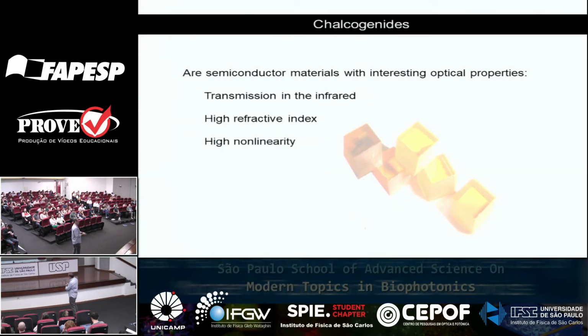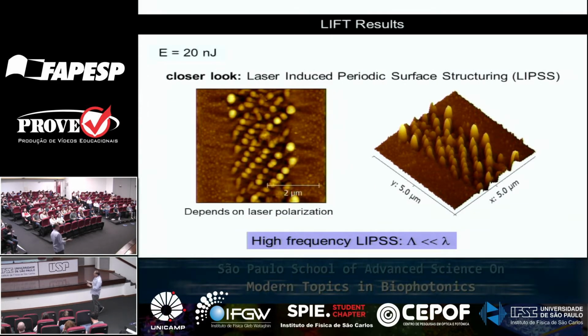In this case, I'm just going to show results for chalcogenides. Chalcogenides are interesting materials, mostly for telecom applications in the infrared. They are transparent up to, let's say, 5 microns, 4 microns. So here, just to give you an illustration, that's the material being transferred. By using 20 nanojoules of energy, those are atomic force microscopy images.